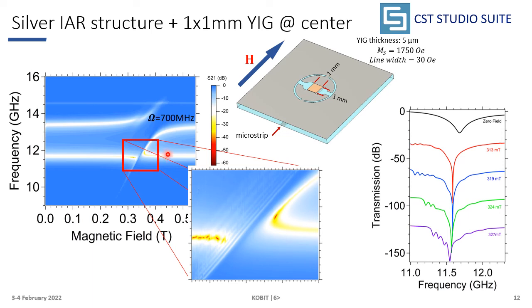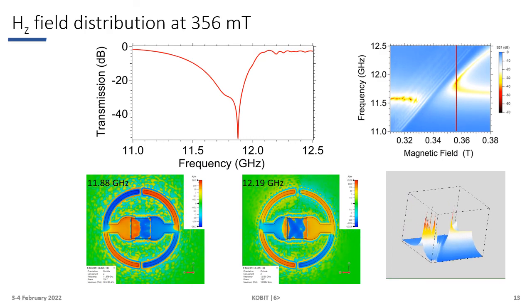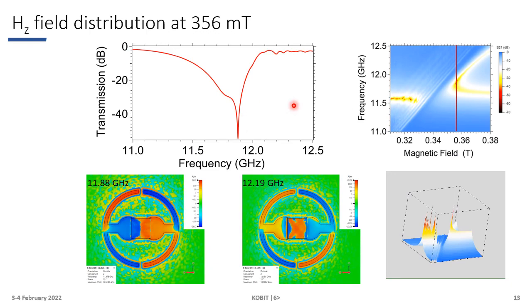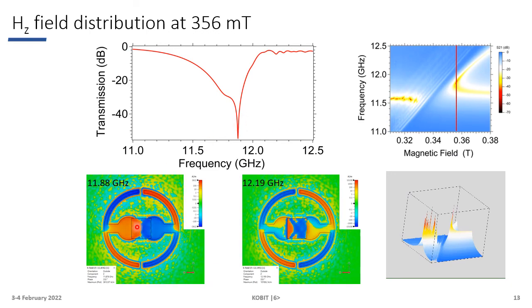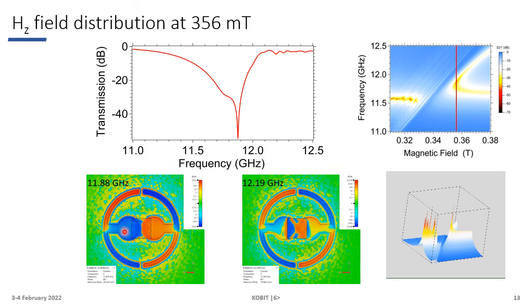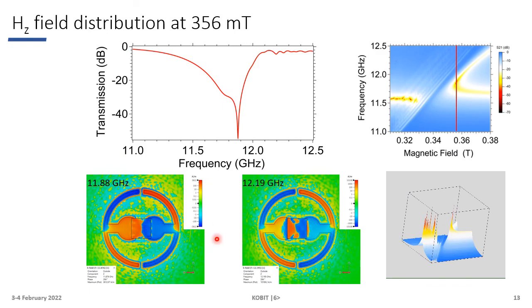When we look closer to the dissipative coupling region, we also see the formation of the magnetostatic modes and the successive coupling of the modes with the first resonant mode of the resonator. And we also see, at the resonant frequencies, the exceptional points where the transmission goes to zero with very narrow line width. When we look at the time domain animation of the Z component of the microwave magnetic field at the multimode resonant frequency, we see the oscillations of the magnetic mode and the resonator mode become coherent at the exceptional points of the spectrum.